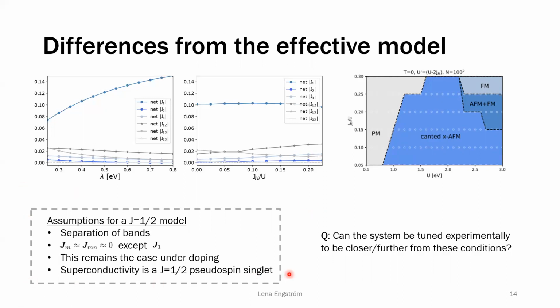So the point here is that this J1/2 model, which was used to predict superconductivity, works under a few very specific conditions. You can have these J1/2 bands, but they must be very well separated from the rest of the bands. For the magnetic order, you expect that only this pseudospin, J1/2, contributes. This is determined at zero doping, and we are assuming for this simplified model that this remains the case even when we dope more. This will also mean that the superconductivity that you see only consists of basically a pseudospin singlet in this J1/2 basis. However, when we characterize what the antiferromagnetic state actually looks like, it seems like there should be other components that are relevant, and that this assumption that we can still use this model seems less valid.